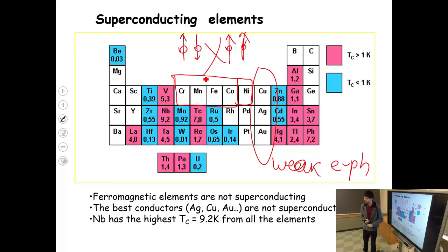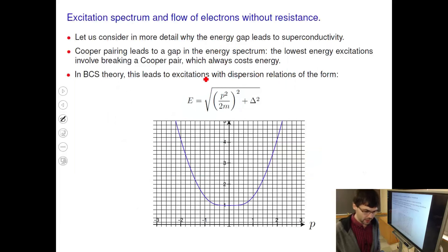So now we understand this. We also understand why magnetic impurities strongly suppress superconductivity. So you take one of these superconducting materials, niobium, molybdenum, and you add a bit of iron, and TC goes down. That's because Cooper pairs flying around see these spins from iron, and they get destroyed. Their correlation gets destroyed due to spin-dependent scattering off of the magnetic impurities. Okay, so that was a very successful theory.